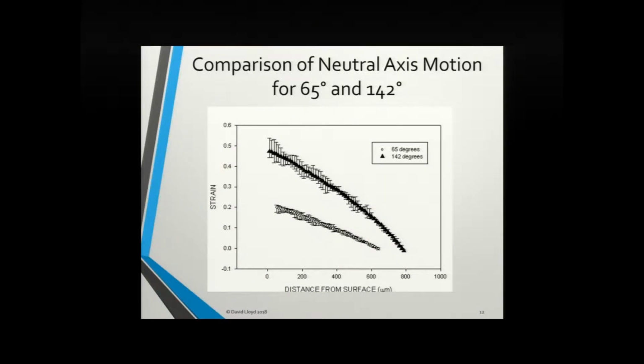This compares the neutral axis motion for a bend of 65 degrees and 142 degrees. This is the 65-degree data. This is the 142-degree data. So you can see that essentially here's the neutral axis at the 0 point, and you can see the neutral axis has moved from that position to that position with the result of the increased bending.